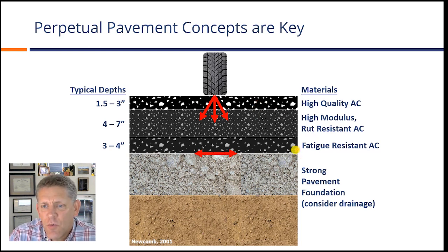And then down towards the bottom of the pavement, we need to think about the fatigue resistance, the cracking resistance of that material, because if we do a good job of that, and we build it just thick enough, we're not going to have enough tension occurring at the bottom of the asphalt to initiate and propagate a crack to the surface of the pavement.